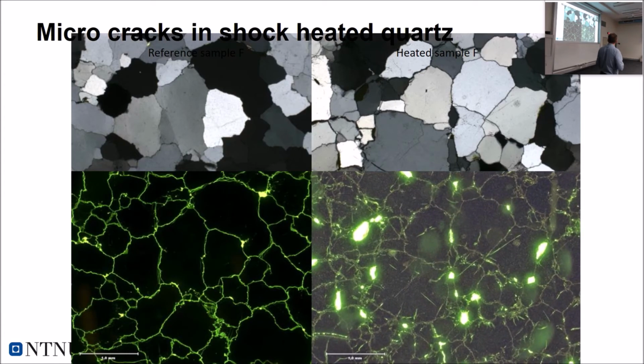After heating for 10 minutes at 1300 degrees, we see that in cross-polarized light, already you can see the difference. You can see that the grain boundaries are not that nice anymore. The appearance of the quartz is a bit more dusty, dirty. And if you go into the UV light with fluorescent epoxy, you see that grain boundaries have become more diffuse. You have some larger pores that occupy a lot of epoxy resin and make the imaging process harder because they fluoresce a lot more.